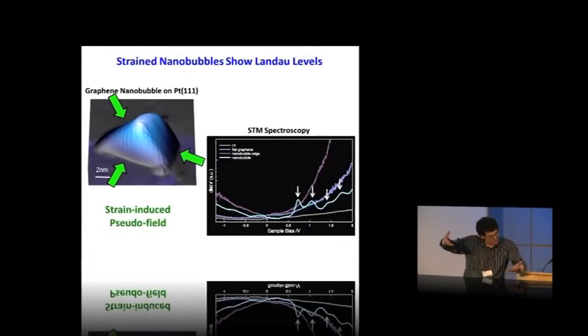Is there any critical angle of the curvature? A typical scale to get a field of one tesla would require a strain of, say, 1% over 1 micron distance. So the fields are so large because these bubbles are so small, and strain within those bubbles, I believe, is 10% or something like that. And when you have a one tesla field, in typical samples on silicon oxide, they're just covered by impurity effects. It can also depend on the symmetry of the strain field. I think we got lucky here. It really has this trigonal symmetry, because it's the 111 FCC.